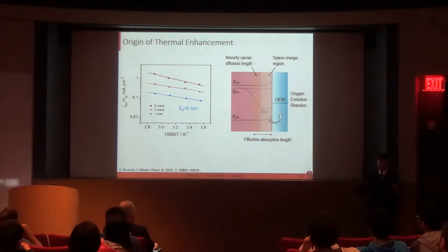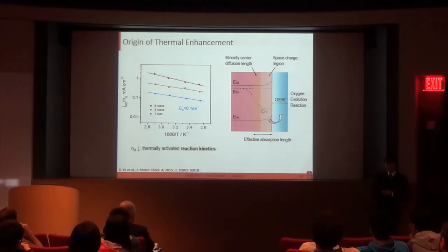The fitting results show that there indeed is a thermal enhancement in such a combined parameter with an activation energy around 0.1 eV. So I attributed this thermal enhancement to the following reasons. First, as you increase the temperature, the reaction kinetics increases, and that causes a faster hole extraction rate at this interface, and that gives you a smaller ideality factor, closer